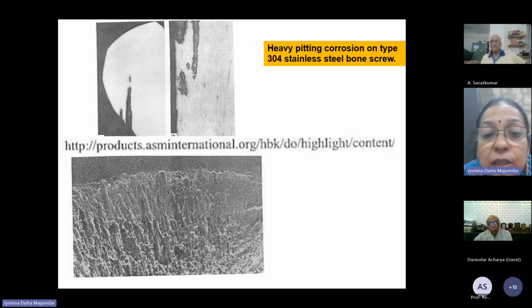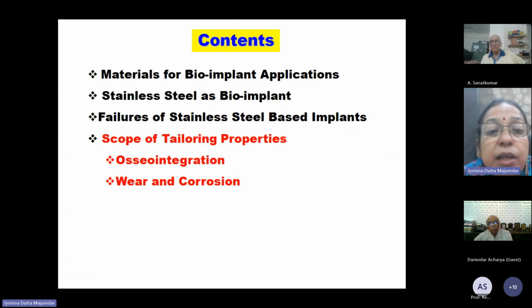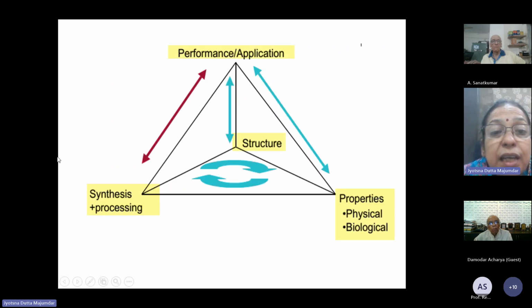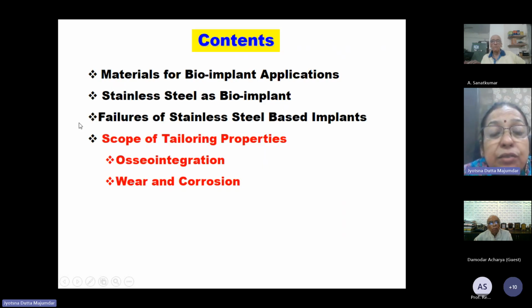So now we are trying to do one small and big project in collaboration with a hospital in Bhopal, where we will try to gather the failed implants and see what the reasons are for the failure of many implants for different applications. If you look at these failures, you'll find that most of them are because of either fatigue failure, or fretting, or a combination of fretting and corrosion, or corrosion and wear. So these are a few reasons for the premature failure of implant material. These failures can be overcome by typical designing of the surface.